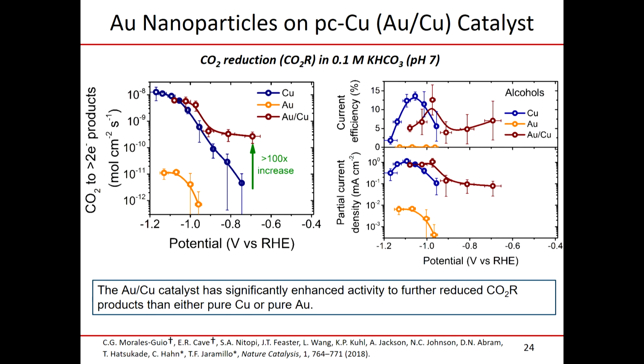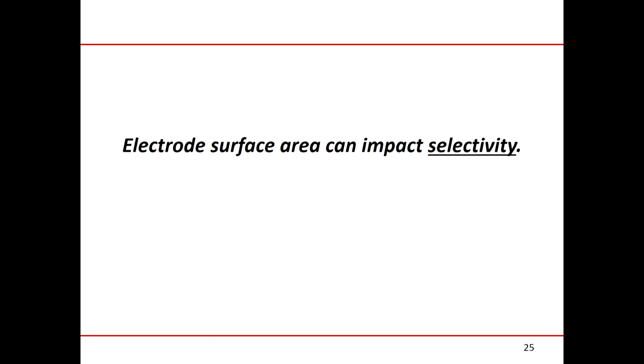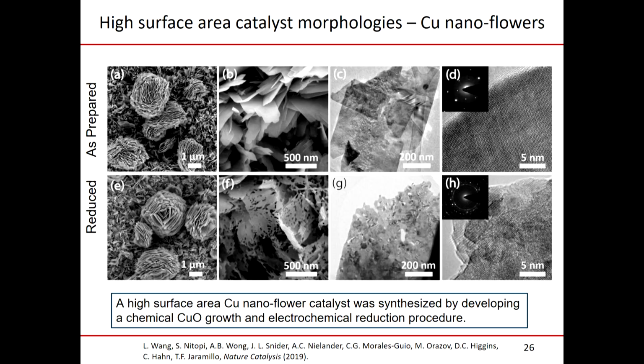And so this is a way of really combining two distinctive catalysts, again, at these molecular length scales, where if you know enough about the mechanism, you can make a better catalyst system. Another interesting output is that electrode surface area itself can impact selectivity, and that's kind of weird. If you want a higher activity and more product, higher surface area makes a lot of sense. In this case, electrode surface area can also impact selectivity for the reasons I mentioned earlier, that if you operate closer to equilibrium, you have less reducing power.